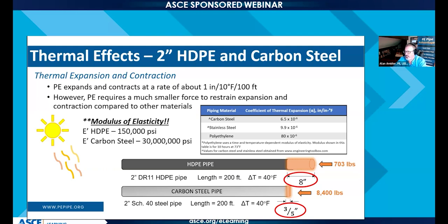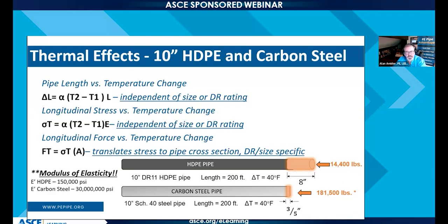However, it would take significantly less force, in this case 703 pounds versus 8,400 pounds, to restrain that pipe from moving. So this calculation is put through to get us a force over the actual wall thickness of that pipe. And the expansion itself isn't a function of that wall thickness or even the diameter, as we'll see from the very next example, that the 10-inch DR11 at the same length will still expand the same amount, but generate significantly larger forces because we're transmitting that stress across the cross-sectional area of the pipe itself. So those are certainly unique properties to HDPE, and we'll talk a little bit more about some of this later, unless somebody wants to add something in particular.